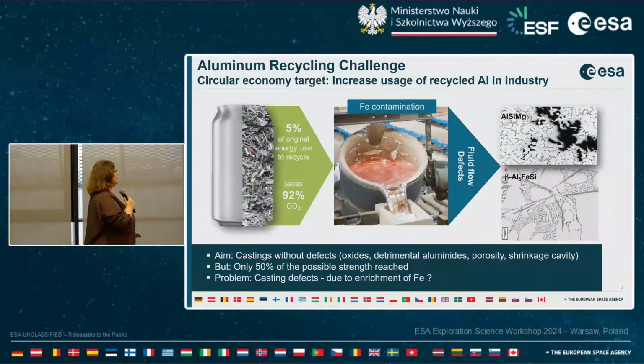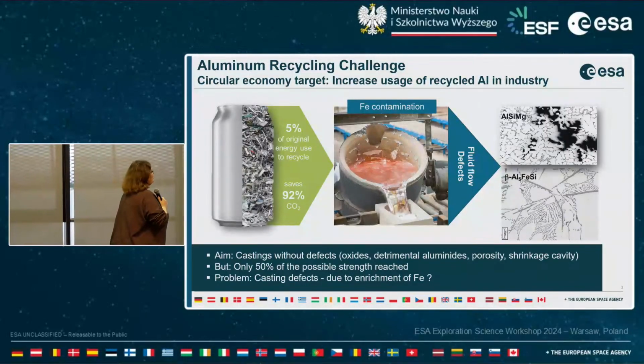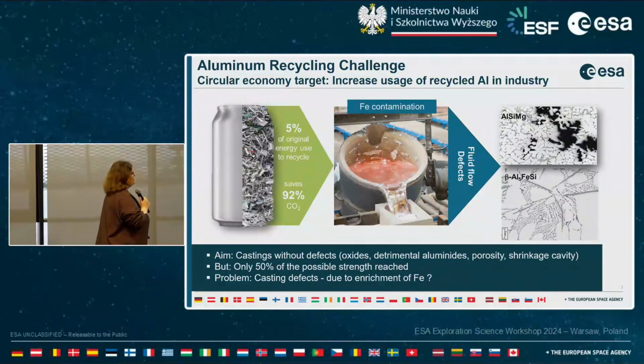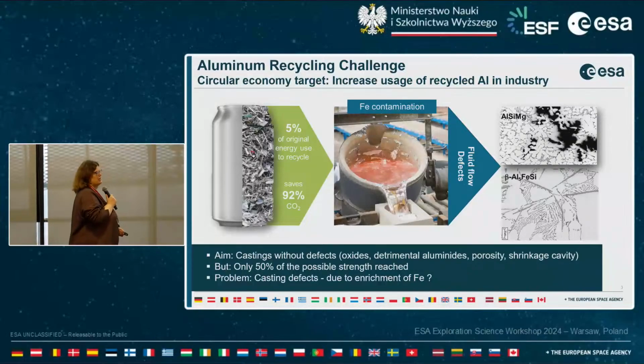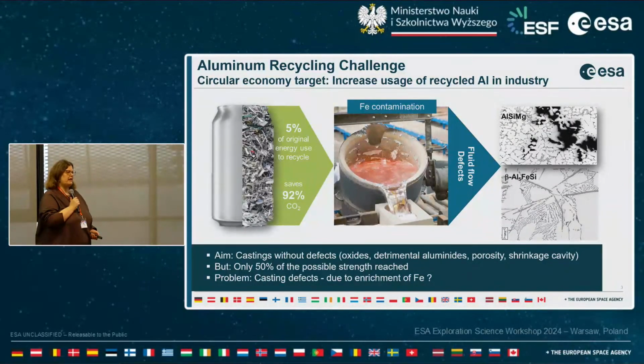But when you talk to the foundries dealing with casting primary aluminum, a mixture of primary and secondary aluminum, or just recycled aluminum, there's always a big but, as always. Because it is well known that in aluminum alloys used as recycled alloys, there's always iron enriched in these types of alloys, and they can economically not fully remove the iron.